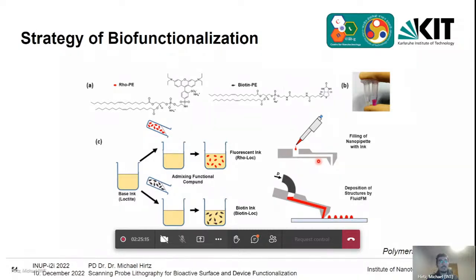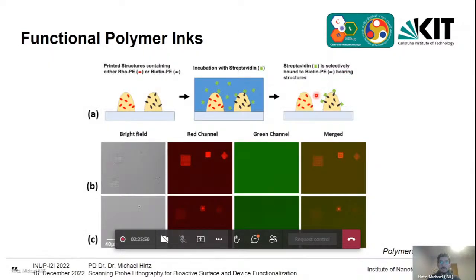Again, here we would also like to biofunctionalize the inks, and here again the biotin-related lipids, or lipids in general, can help. Because now you can think of it: if we print such a polymer and we want to have the biotin molecule on the outside of the polymer, one of the approaches would be to take a surface active agent like the lipid, because it has hydrophobic and hydrophilic parts, and hope that this will assemble at the interface between the ink structure and the outside. And this is actually what we observed happening. So enough of the biotin material sticks out of the printed structures.